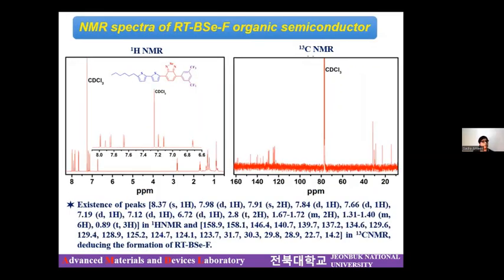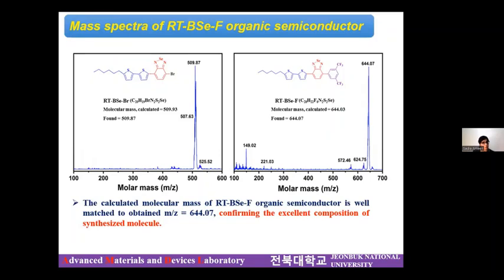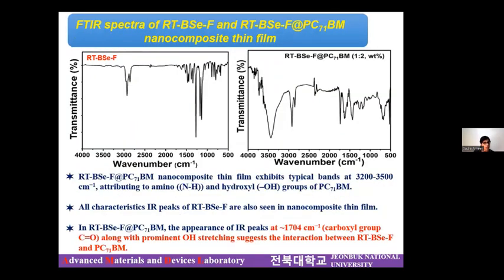We have also performed the proton and the carbon NMR for the final product. And after that, we performed the mass spectroscopy. From the mass spectroscopy, the interesting thing we have found is that the molecular mass for the calculated as well as the found one is almost the same for both the intermediate as well as the final product, which confirms the excellent composition of the synthesized molecule.